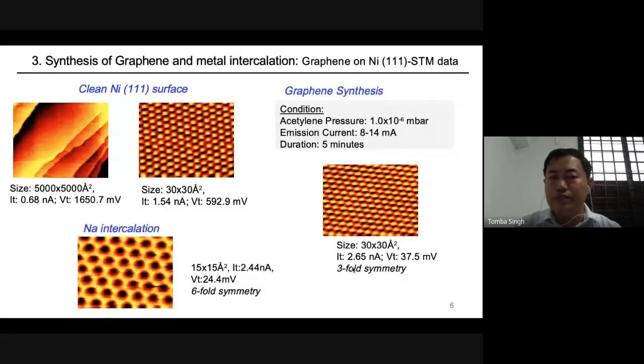Here, I would like to discuss how we synthesize graphene on metal substrates, typically on a nickel single crystal surface. As I mentioned, we need a very clean surface. We do this with repeated cycles of sputtering and annealing. What is sputtering? It is argon bombardment of the surface. Then we heat it using an electron beam. We use a filament, the electrons are ejected and strike the surface, and the surface becomes very clean. The surface cleanness can be confirmed using STM, XPS, or low energy electron diffraction.